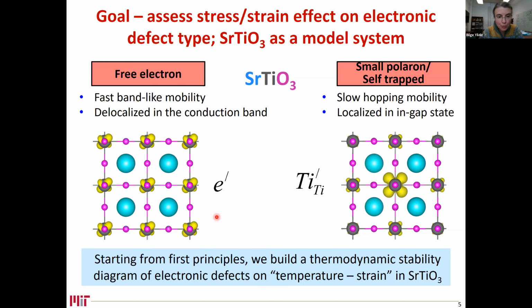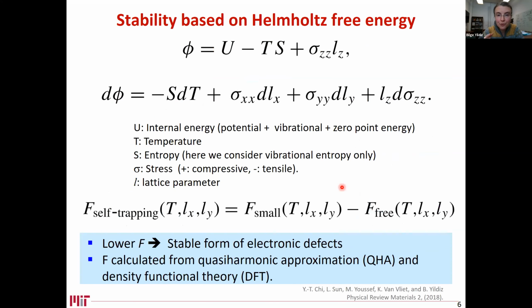And by combining first principles calculations with thermodynamic analysis, we could produce a temperature-stress or temperature-strain map to identify the stability regimes of these two different types of electronic defects, which have different implications for electronic conductivity. And for such a problem, the appropriate potential to assess the system in is the Helmholtz free energy, which gives us the free variables as the temperature, the X and Y lattice parameters of the material, such as in strained oxide thin films, as well as the stress along the Z-axis that the film would relax.